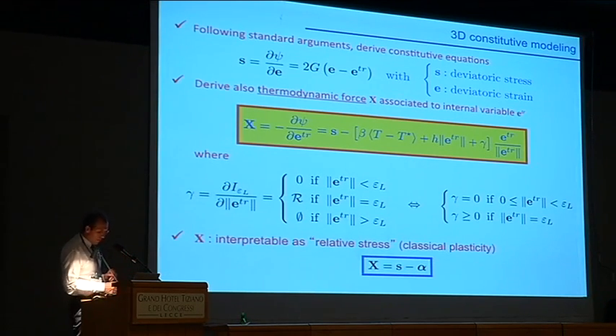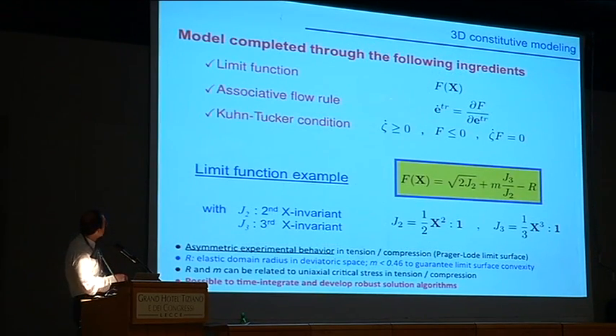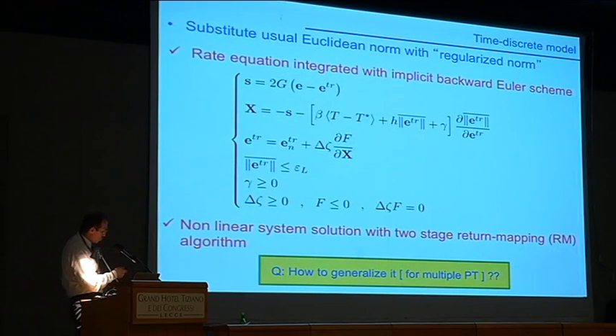Once we derive the deviatoric part of the stress and the thermodynamic force X, borrowing concept from classical plasticity, we can introduce a limit function, we can introduce an associative flow rule, and the standard Kuhn-Tucker condition, and clearly we can choose also quite a nice limit function, very classical from the plasticity world. Okay, so that's a very simple model. Once we develop all the equations, we can start to play with the model. In particular, as I say, the first thing you have to do is to regularize the norm, because you have the norm at the denominator, so you don't want to have something divided by 0.